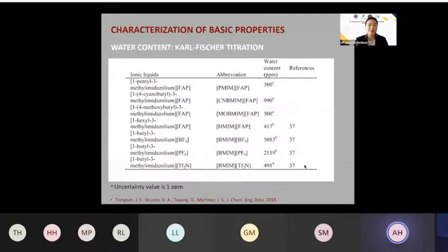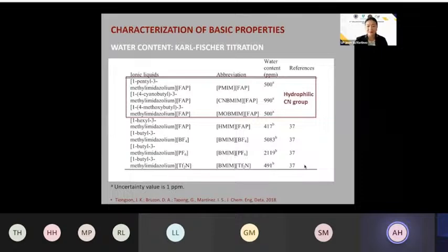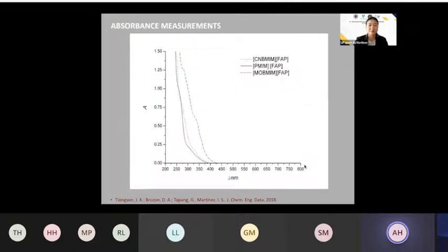And of course, the next slides are just different experiments that we have done to characterize the ionic liquids that we have synthesized. We start with the amount of water in our ionic liquids. So we use Karl Fischer titration. And as you can see here, our values are quite low and comparable, of course, to known hydrophobic ionic liquids. And among the 3 ionic liquids that we have synthesized, the CN functionalized is the most hydrophilic one, probably, of course, because of the presence of the nitrile group.